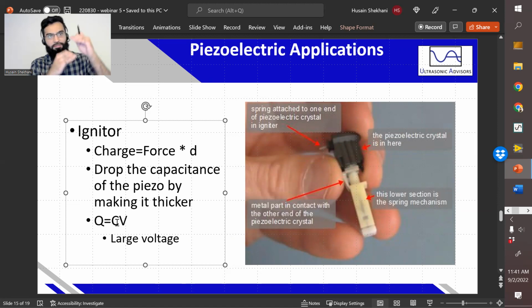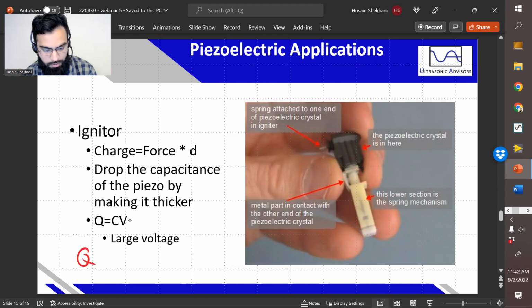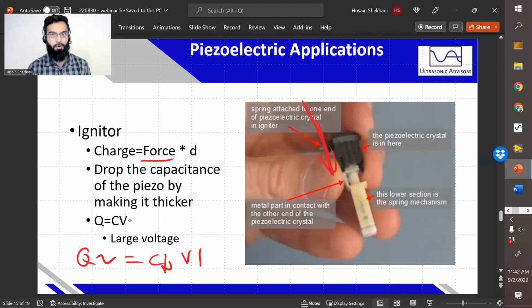So if you make a capacitor thicker, you drop the capacitance. In this case, if you drop the capacitance and you're generating a set charge, the voltage has to increase. So the Q is about the same. If you provide a set voltage or a set impact, you're dropping the capacitance, so the voltage here has to increase. That's how you can generate sparks from a simple kind of igniter, which creates an impulse force from a loaded spring onto your ceramic, and that then will create the large voltage that you need to ignite your flame.